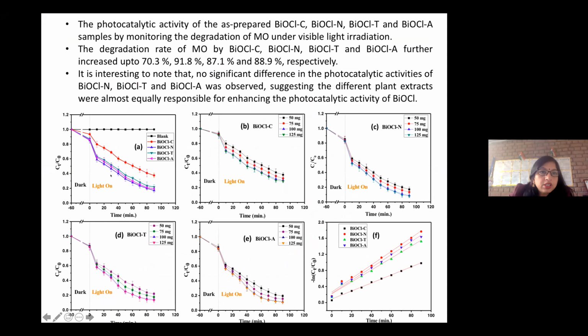So in the first process, this is the blank graph, and then the chemical one means like the hydrolysis. C is showing without any green process, so we have represented it by C, meaning chemical one, and then NTA. So they showed better results than this red one. So degradation was more in the case of the green one. So it means that only these leaves are responsible for enhancing the separation of electron-hole pairs, inhibiting electron-hole pair recombination, and moreover they are enhancing photocatalytic activity.